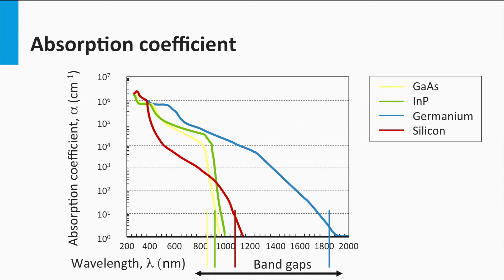Gallium arsenide has the highest band gap, as it starts to absorb light at the smallest wavelength, or the highest photon energy. Secondly, if we focus on the visible spectral part from 300 nm up to 700 nm, we see that the absorption coefficient of indium phosphide and gallium arsenide is significantly higher than that for silicon. This is related to the fact that indium phosphide and gallium arsenide are direct band gap materials, as discussed earlier.